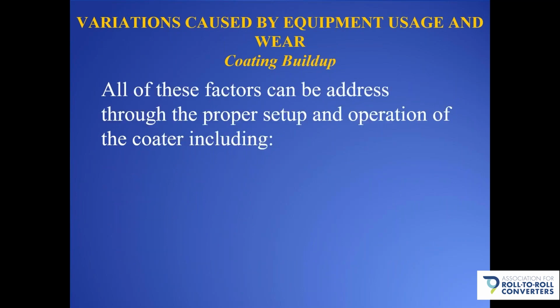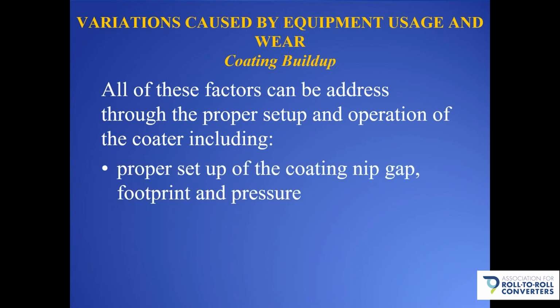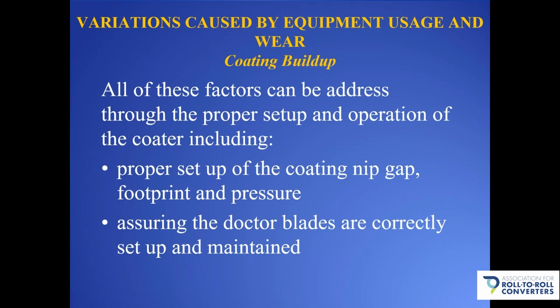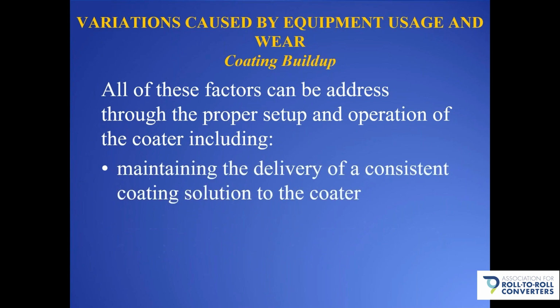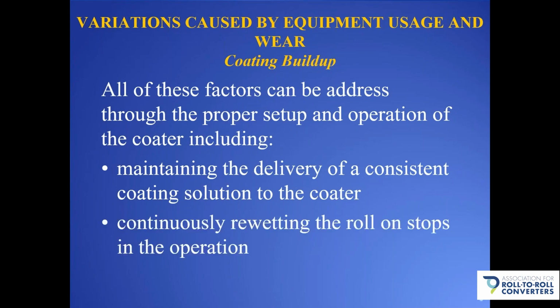Now, all of these factors can be addressed through the proper setup and operation of the coater, including proper setup of the coating nip gap, footprint, and pressure to make sure that you get good release of the coating from the cells, assuring that the doctor blades are correctly set and maintained, maintaining the delivery of a consistent coating solution to the coater, and continuously re-wetting the roll on stops in operation so that the coating doesn't dry in the cells.